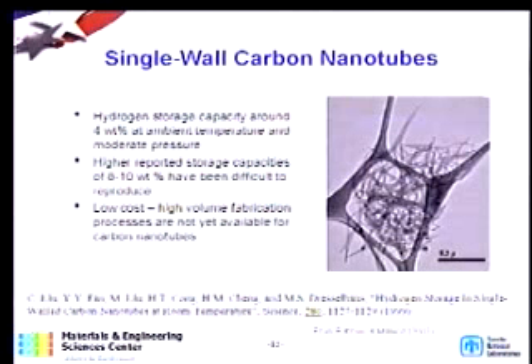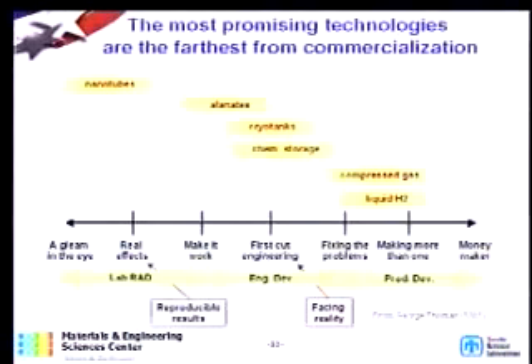Of course, the nanotube is a very attractive one. Everybody would like to make sure that it will work. Currently, I think the official language is that up to 4% has been shown, but higher than that has not been demonstrated or reproduced. DOE still likes to continue working on it. I think there's maybe more controversy about contamination or other metals as a catalyst that absorb more hydrogen than carbon, but that's an open issue. So if you put it in perspective in terms of maturity, of course, compressed gas and liquid hydrogen are the most mature ones, and then go beyond. The analytes here are trying to make it work, and the nanotubes we think are still far out.